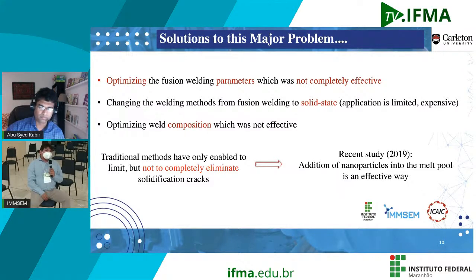Or we can control the welding parameters. So optimizing, if we control the fusion welding parameters, we are never going to get rid of the solidification cracks completely. It's impossible. If we change it to a solid state welding process, the application is limited, and it is very, very, very expensive because the friction stir welding process is very expensive itself. And the third way we can do that is by optimizing weld composition, which was not effective either.